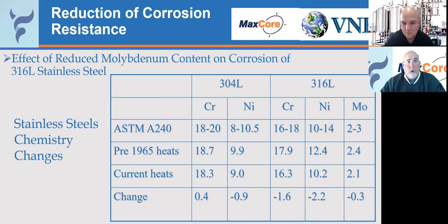After 1965, they were able to start controlling these alloying elements a little bit better. If you look at the current heats coming in now, you're looking at about 16.3% chromium, 10.2% nickel, 2.1% molybdenum. So basically, the overall mean corrosion resistance of the material has dropped over the last few years, because they're able to control those alloying elements down to the bare minimums to meet the ASTM standards. And what replaces that is iron. As the elements that give us the corrosion resistance have dropped, the iron content has gone up, and therefore it creates an issue, and we don't have steel that lasts in the same applications it may have looked at 60 years ago.